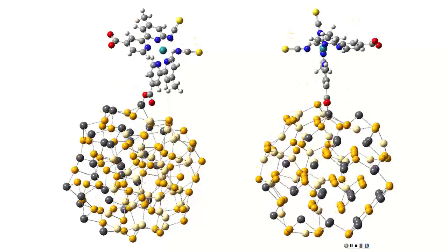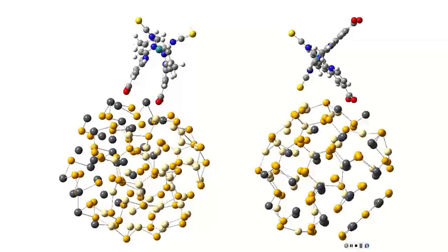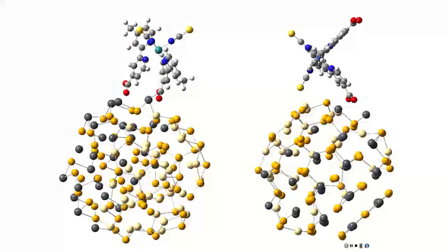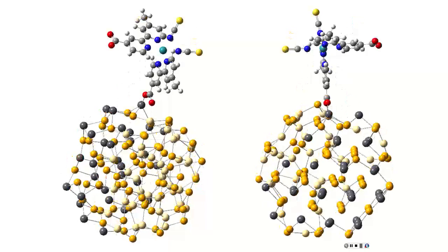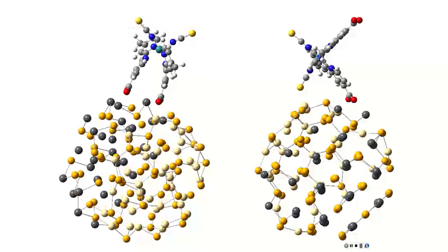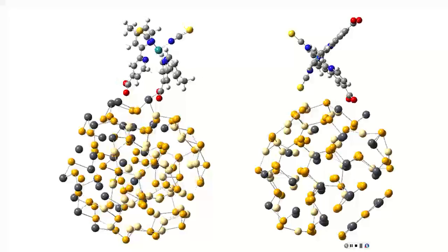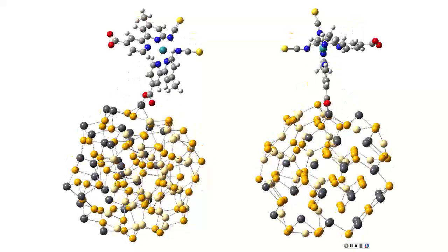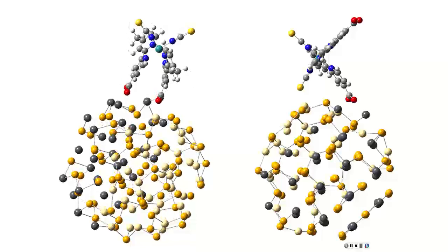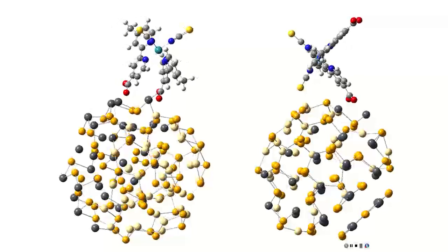This already splits your positive and negative charges differently, and more so when you have different materials, lead and cadmium, rather than just a surface with only lead and selenium, or only cadmium and selenium. So at the interface you expect a much bigger dipole moment than on just this surface or that surface. Although the dipole of cadmium selenide is higher than the dipole of lead selenide.